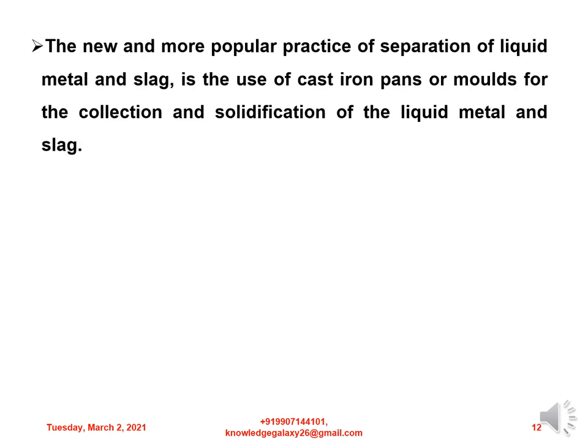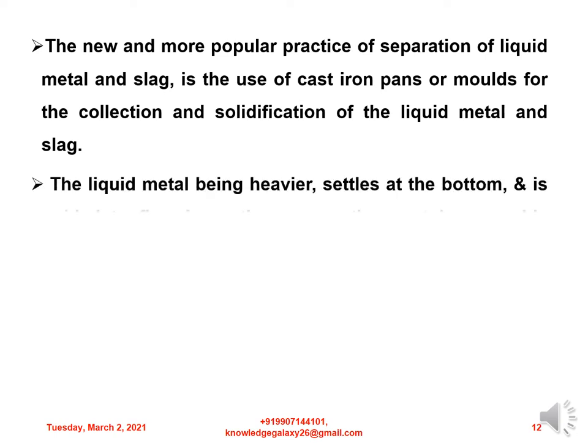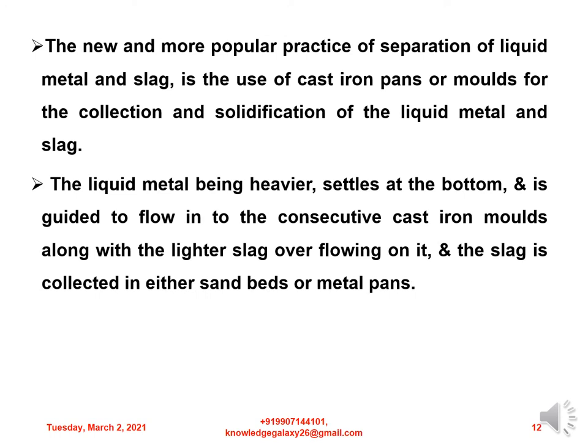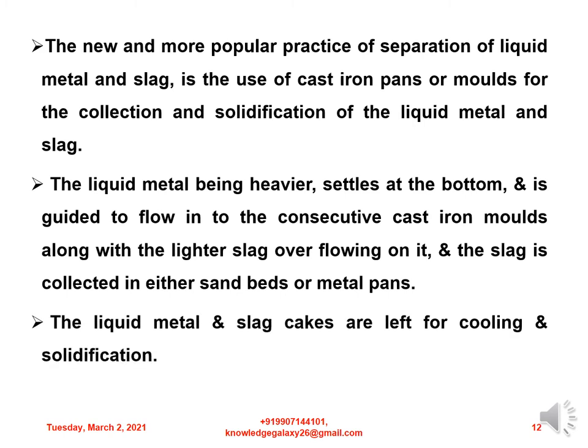The newer and more popular practice of separation of liquid metal and slag is the use of cast iron pans or molds for collection and solidification. The liquid metal, being heavier, settles at the bottom and is guided to flow into consecutive cast iron molds, with the lighter slag overflowing on it; the slag is then collected in either sand beds or metal pans. The liquid metal and slag cakes are left for cooling and solidification.